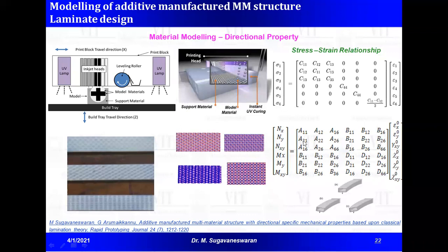So based on this relationship, the A matrix represents axial loading, the D matrix represents the moment, and the B matrix represents the coupling between axial and moment. Certain terms in this ABD matrix can be made zero, and in certain layup sequences we could also achieve a symmetric condition in the laminate. That is, above the mid axis and below the mid axis, we are able to achieve a symmetric condition.